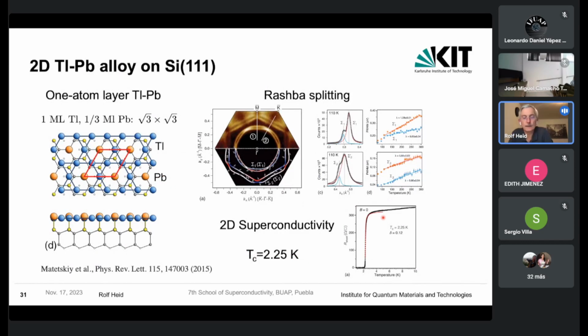And the third and final system I would like to discuss is a variant of the first one I've shown, which is a kind of 2-dimensional alloy on top of the silicon 111 surface. In that case, the previous 1/3 monolayer lead structure is modified in such a way that the lead atoms in a hollow site of this silicon surface are replaced by thallium atoms. And this can be done experimentally in a very well-ordered fashion, and has been analyzed also by ARPES measurements shown here, where they nicely see Fermi surfaces of this ultra-thin, single atom layer system.